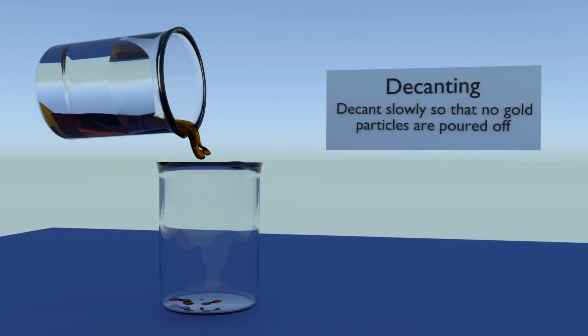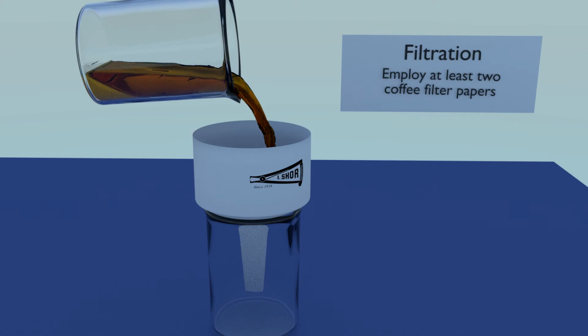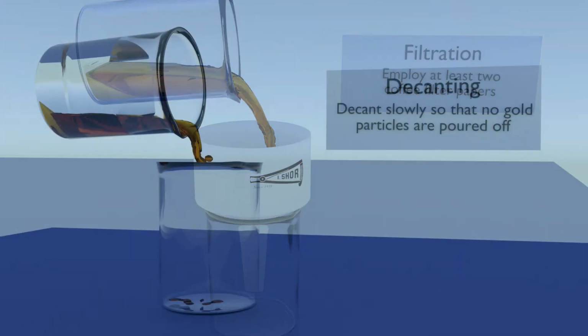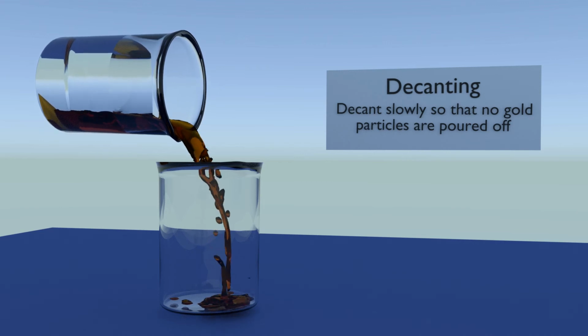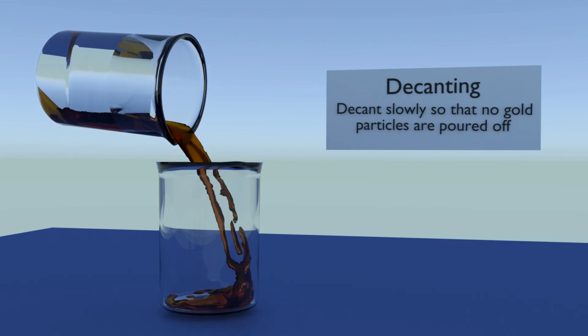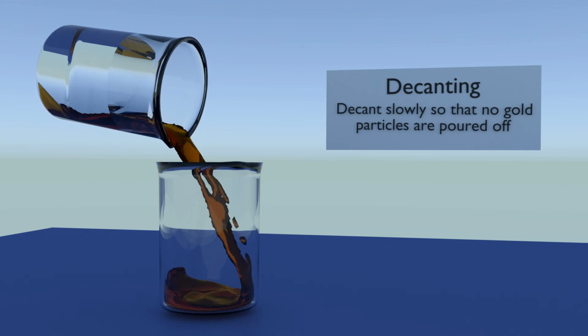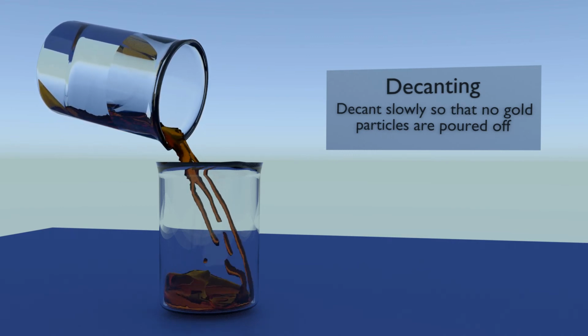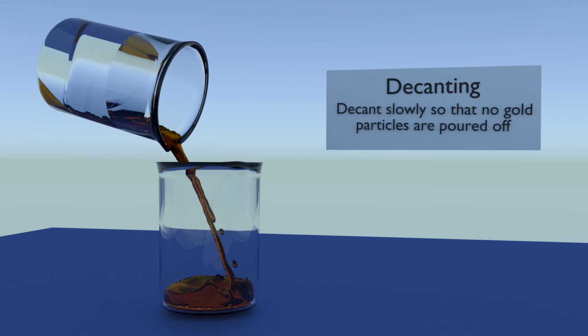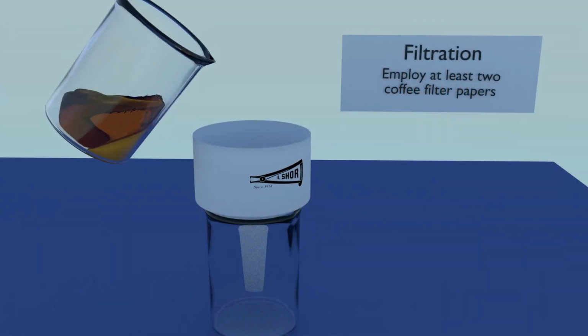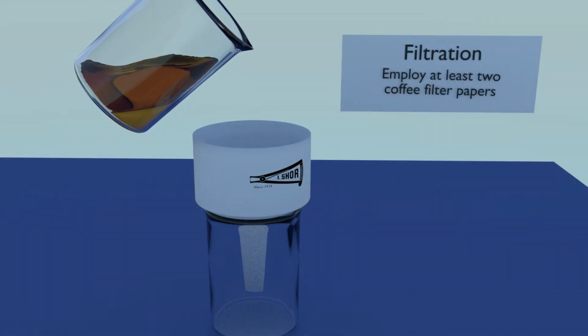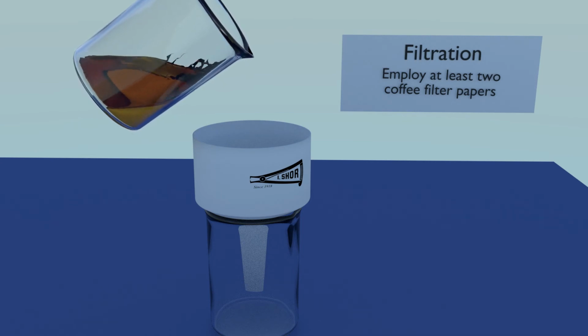Decanting or filtering. Once the solution has been tested for dissolved gold, and the test confirms that the solution is free of dissolved gold, it is time to either filter, or decant, to recover the gold particles. It is generally considered simpler and easier to decant the solution, rather than to filter it. To decant the solution simply means to pour the solution off slowly and carefully. If filtering, use a Buchner filter funnel with at least 2 layers of coffee filter paper.